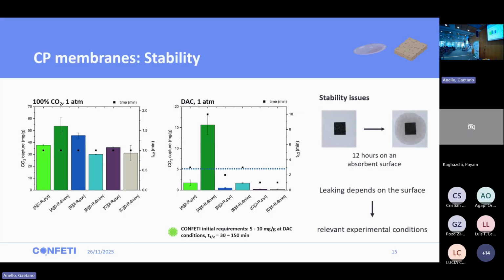So it depends on the surface where this material takes place. For example, you have here an example of an absorbed surface. It's a cellulose paper. We can observe the leakage of the ionic liquid from the material. So the porosity of the carbon paper helps in the CO2 accessibility to the ionic liquid, but it cannot retain the ionic liquid inside. So to solve this, we decided to introduce a third approach.